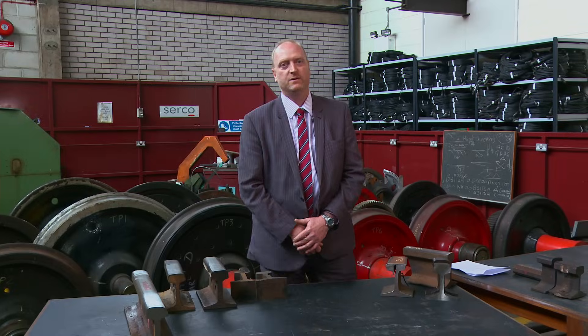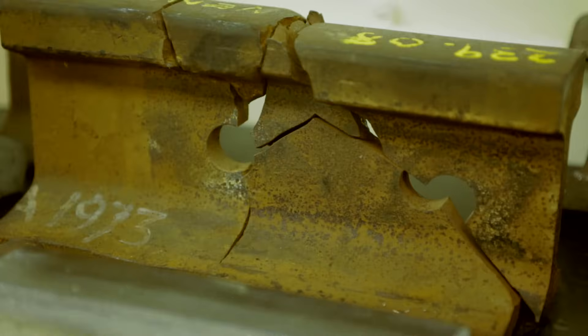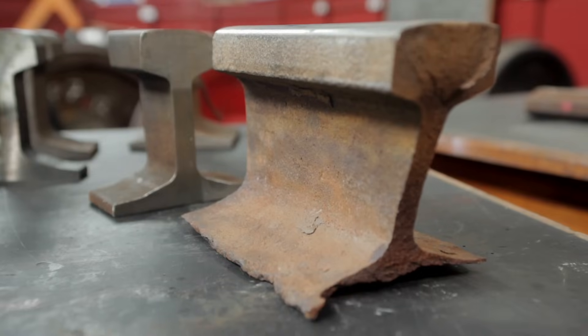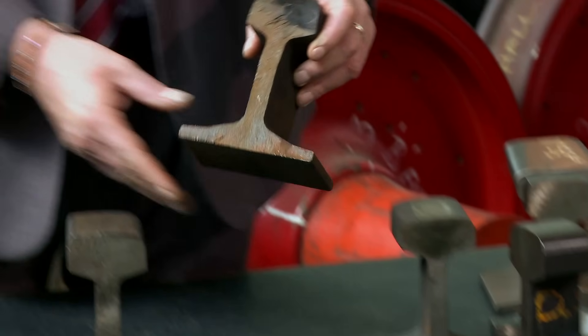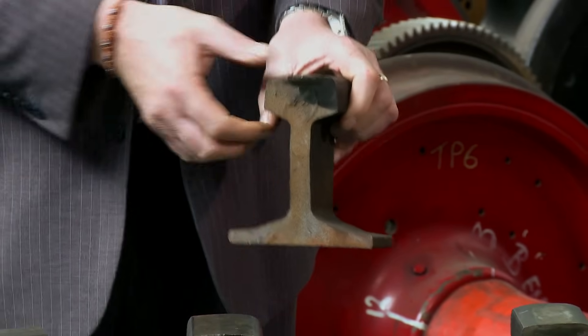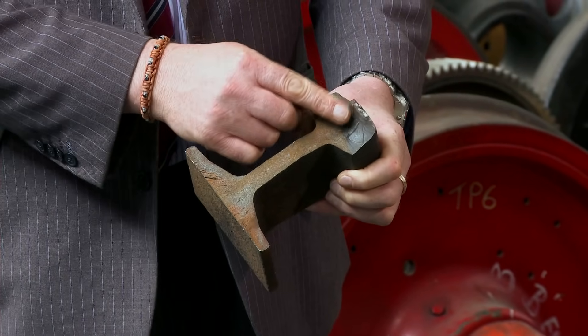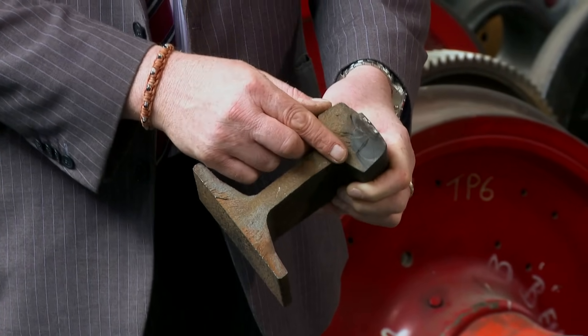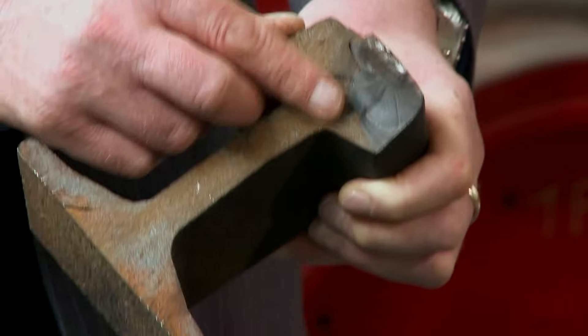There are four main types of degradation we see with rail. There's fatigue damage on the surface and internally within the rail. There is wear, both head and side wear. There is also plastic deformation of the rail and a loss of section due to corrosion. This sample here shows a fatigue crack which is initiated from the surface of the rail. It's caused by the repeated passage of wheels over the surface, which initiates small cracks that through fatigue grow progressively over a long period of time. The discolouration and clamshell markings visible are a result of the surface becoming oxidised and corroded where it becomes exposed to the elements.